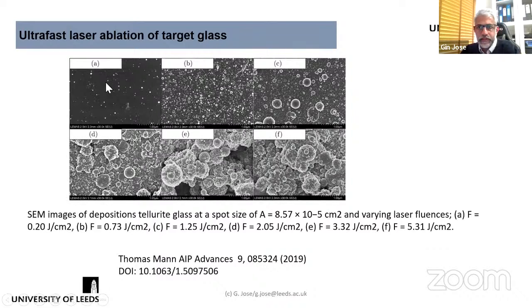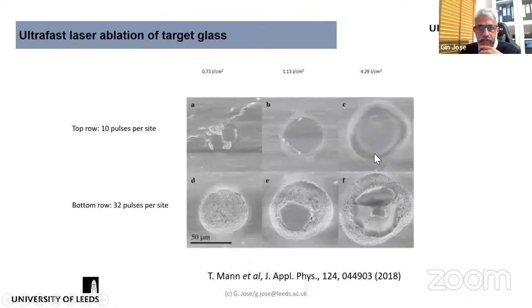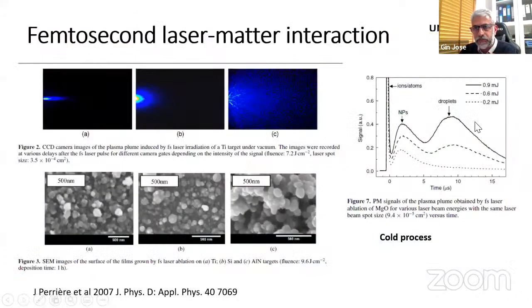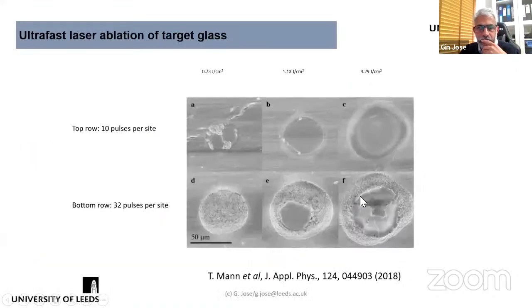So here you see the fluence for A is like 0.2 joules per centimeter square. So that's the lowest. You see some particles at the surface, but it's not fully covered. There may be smaller particles which you cannot see in this SEM image, the scanning electron microscopy image, as well. As you increase the fluence, you have more particles, and you will also see larger and larger clusters forming, or larger particles coming up as well, which is correlating to the result I have shown there. Maybe droplets coming out of the target.